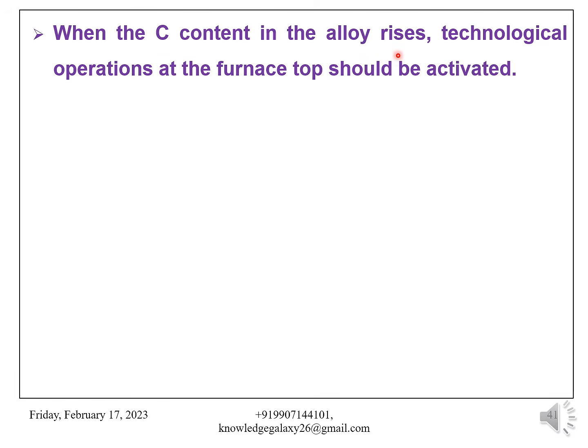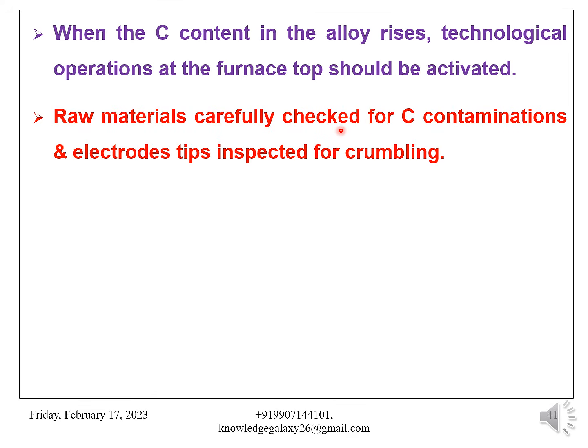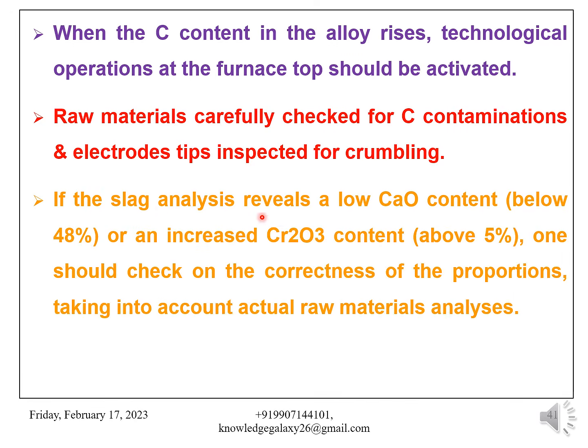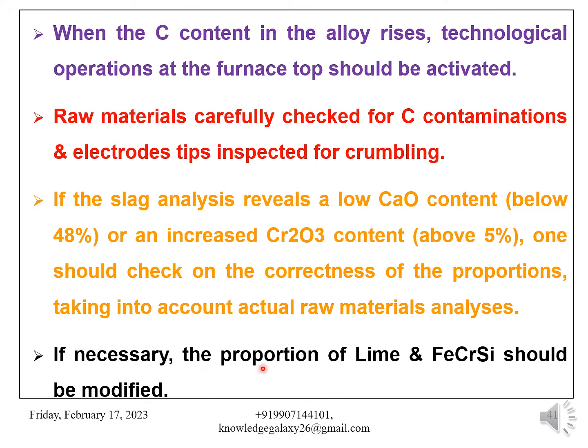When the carbon content in the alloy rises, technological operations at the furnace top should be activated. Raw materials should be carefully checked for carbon contaminations and electrode tips inspected for crumbling. If the slag analysis reveals a low CaO content, below 48%, or an increased Cr2O3 content, above 5%, one should check the correctness of the proportions, taking into account the actual raw materials analysis. If necessary, the proportion of lime and ferrochrome silicon should be modified.